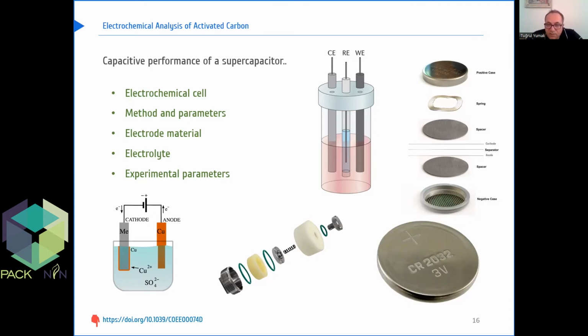Besides, the thickness of the electrode is also a determinative parameter of the capacitance, and commercial cell electrode thicknesses range from about 10 micrometers thick for high power density to several hundred microns thick for higher energy density.